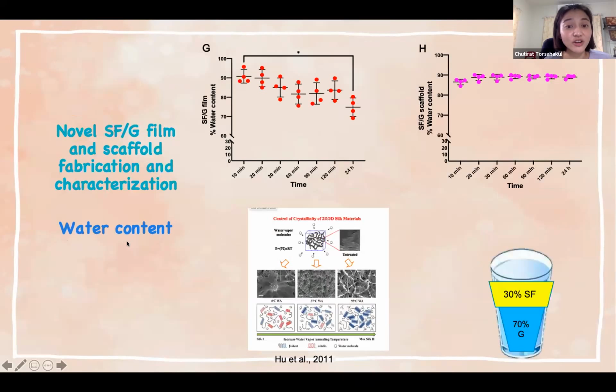And the next part is the water content of the silk film and sponge-like scaffold. In the film, the water content is up to 90% and gradually decreases over time. And the SFG scaffold is up to 85% at the first time point. The gradual decrease over time can be explained by the percentage of gelatin in the film. There is 70% gelatin that is non-cross-linked, so some of the gelatin dissolves in the water. And for the next study, we suggest using a higher temperature for cross-linking the SFG film. In this study, if we raise the temperature to 95 degrees Celsius, the silk film can form beta-sheet better and be stronger.